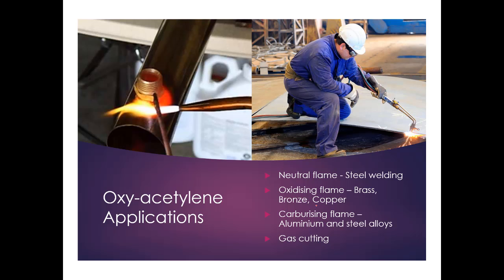When it comes to applications, we use our neutral flame most commonly. It's the most often used type, mainly in steel welding. We use an oxidizing flame, remember, where you have excess oxygen, on brass, bronze and copper. In other words, we're using those on non-ferrous metals. We need more oxygen there to help burn away impurities. We use the carburizing flame, which has less oxygen, on aluminium and on steel alloys such as stainless steel.